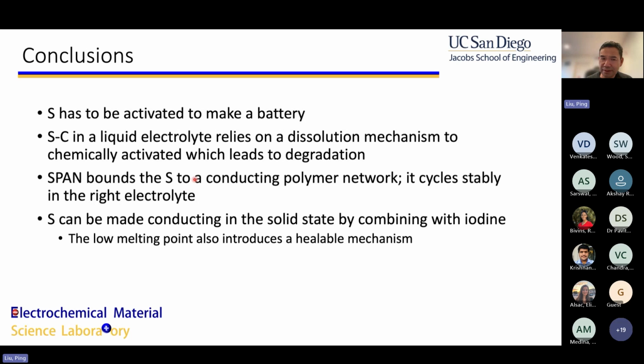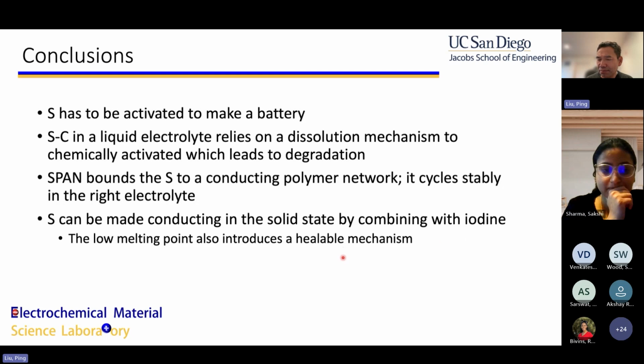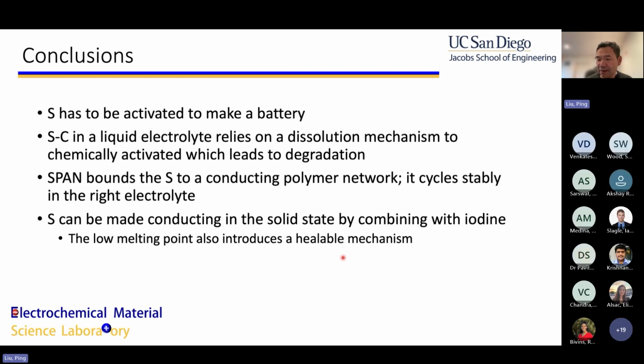This problem can be solved in two different ways. You can put the sulfur onto a polymeric structure that will give it conductivity. With the right electrolyte, the material actually cycles very well. There's a limit to how much sulfur you can put on there, which limits the energy density of the battery. Alternatively, you can also study sulfur as a subject of material science. In that case, we use doping. We make new sulfur-containing materials. This is not really doping. Sulfur iodine, the superlattice, is a brand new material. And this material has better electronic conductivity, and its melting point is also low, so that it can partially heal itself.